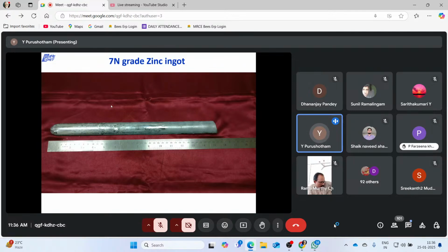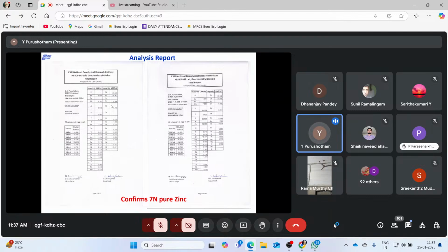What happened during this project? Actually, this was sponsored by BRNS and IGCAR, Indira Gandhi Center for Atomic Research, Kalpakkam. They asked us to make not only ingots, but they had to be converted into granules. So here, we have to prepare granules of less than 3 mm diameter of 7N grade, and that has to be supplied. Then after zone refining, we have to analyze. This is an HR ICP-MS at NGRI. We analyzed, which confirms 7N pure zinc.